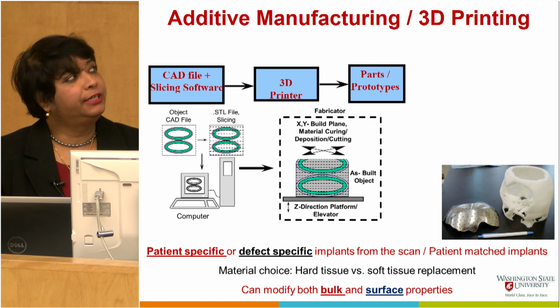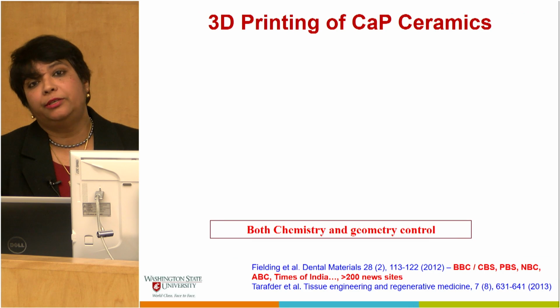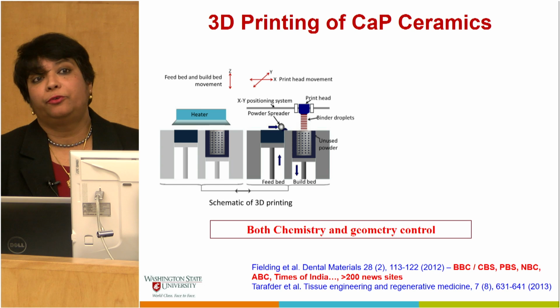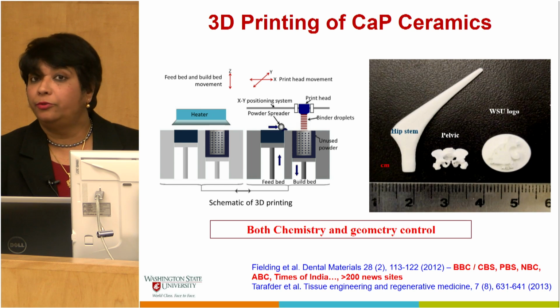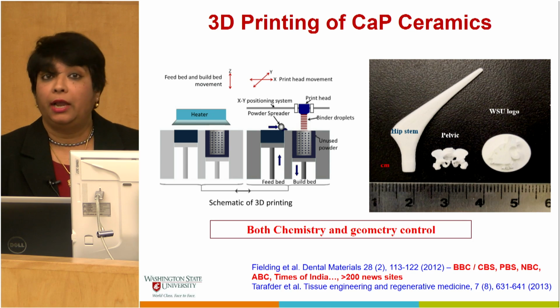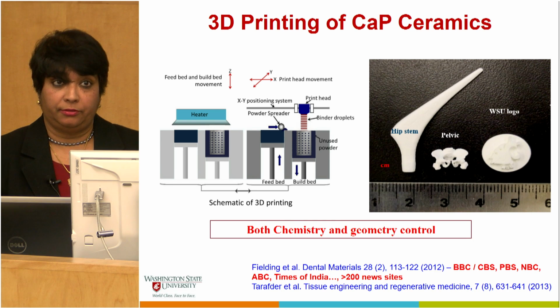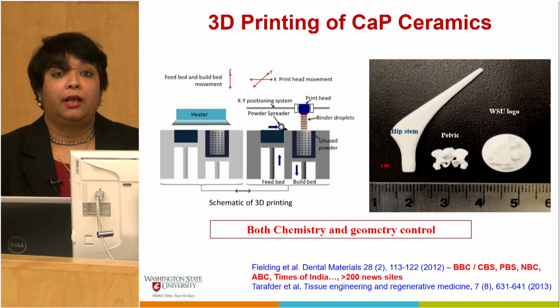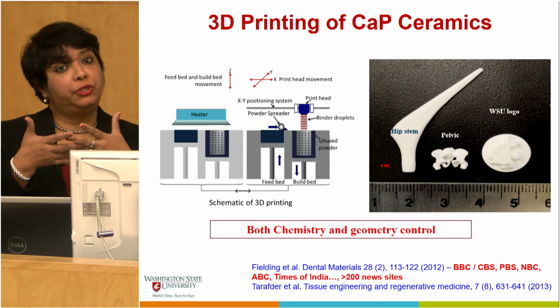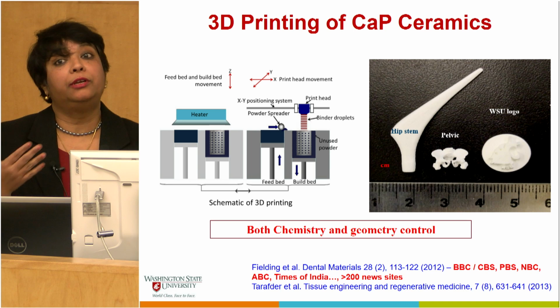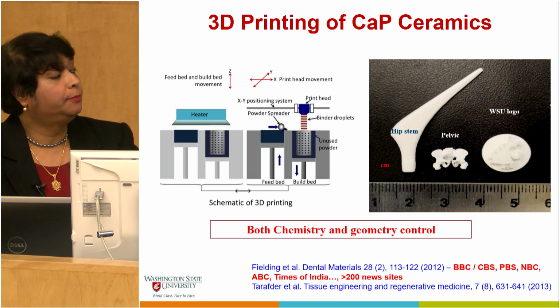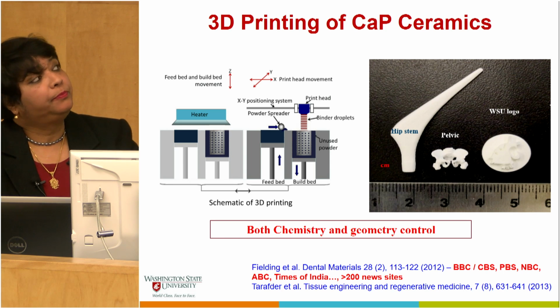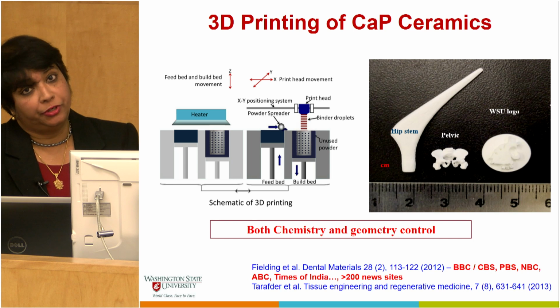If you notice 3D printed implants, you will see that oftentimes they are made porous, and the primary reason is, one, it can reduce the weight where you do not need weight, and two, sometimes the pores on the side give the surgeon the flexibility to use a suture. And three, of course, if you are using 3D printed scaffold material, it also helps with host tissue growth as well as blood vessel formation and nutrient transport. So using a 3D printer, you can control both chemistry and geometry of a part.